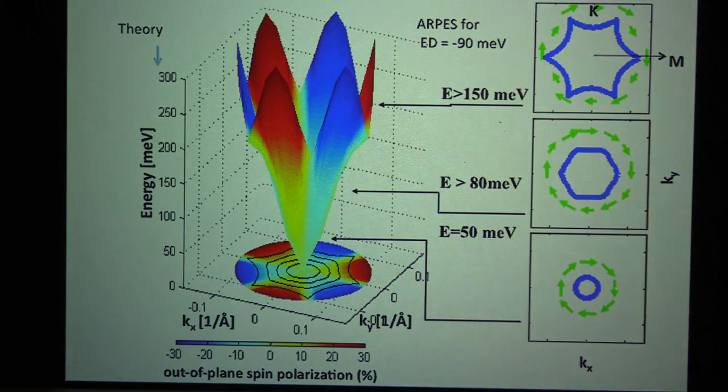And in fact, as I told you, as you go from near the Dirac point to high energies, the Fermi surface changes from circular to hexagonal to snowflake-like. Interestingly, when it's a circle, remember I just showed you that the dominating process that we see in STM is backscattering. Backscattering is prohibited in these systems, so as long as the Fermi surface looks like a circle, we get no signal, which is like indirect proof that backscattering is prohibited. Okay? So in these systems, we can only get information using QPI at high energies.